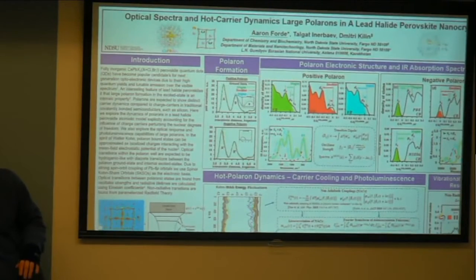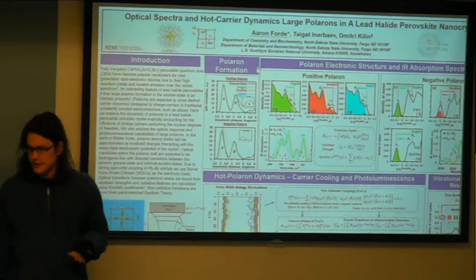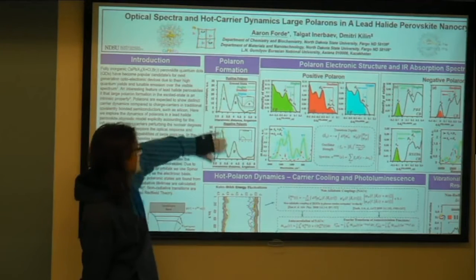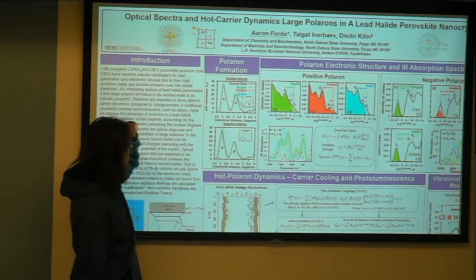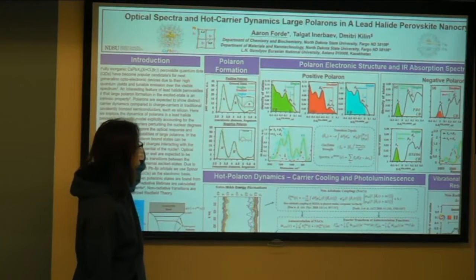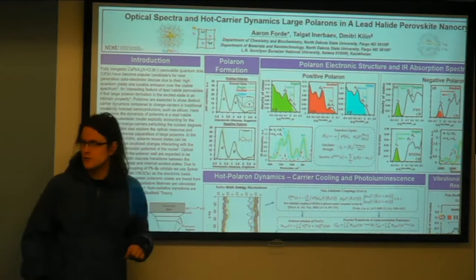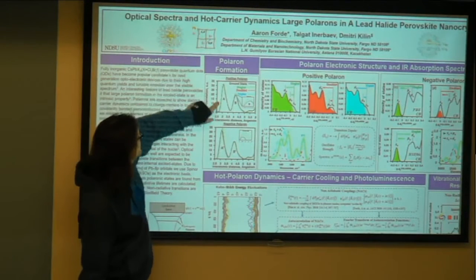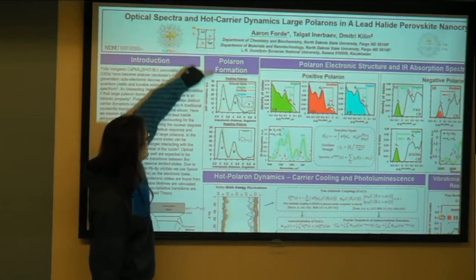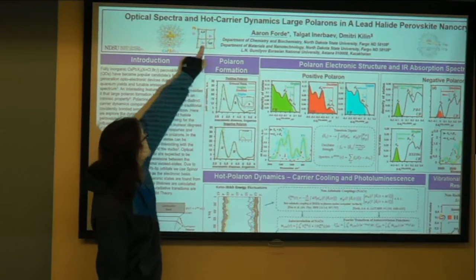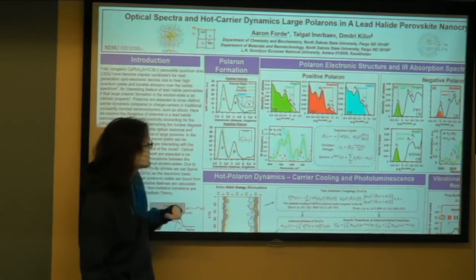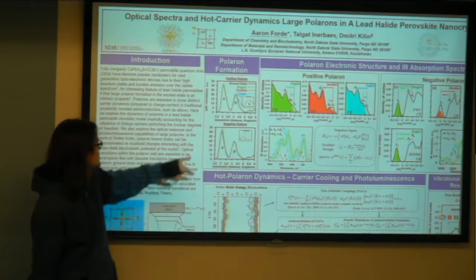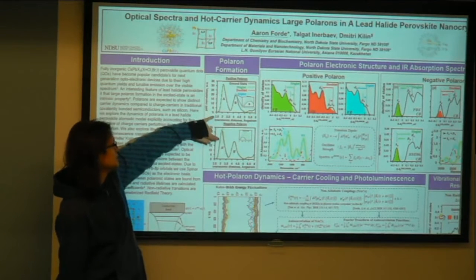And so if you're talking about polaron formation, you'd expect changes in the nuclear coordinates for each charge. So that's what is plotted here. These are radial distribution functions, which describe coordinations between the lead and the bromine, as illustrated here. So these A peaks are lead-to-bromine coordination distances, and B is bromine-to-bromine. And the big thing that we noticed with these is that for each charge, you would only see changes in one of those